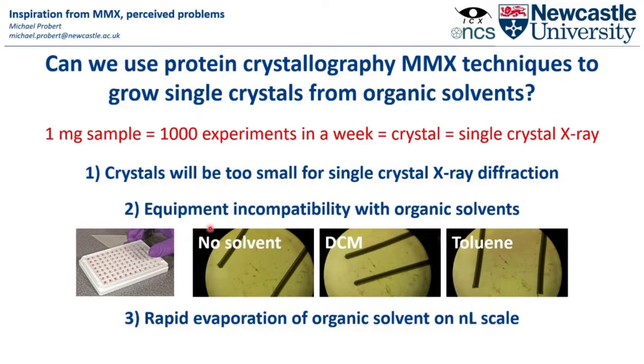There was no discoloration, there was still structural integrity, and we knew that the contact time of our solvents with the plastics was very, very small in any dispensing situation. It's of the order of seconds rather than the order of days. And because those dispensing tips are disposed of, there's no contamination from one system to the next, and there's no worry about degradation of the performance of the liquid handling robots over time, at least caused by the solvents. So our big issue then is this rapid evaporation of organic solvent on the nanoliter scale. So that's something we really do need to get a handle on.